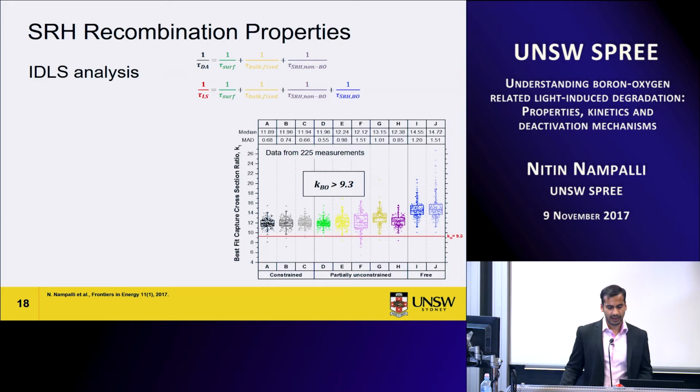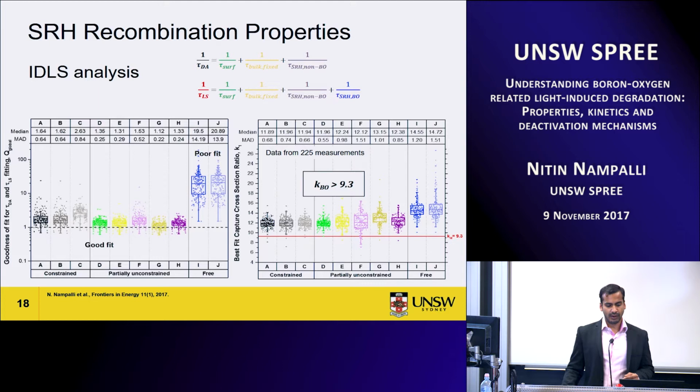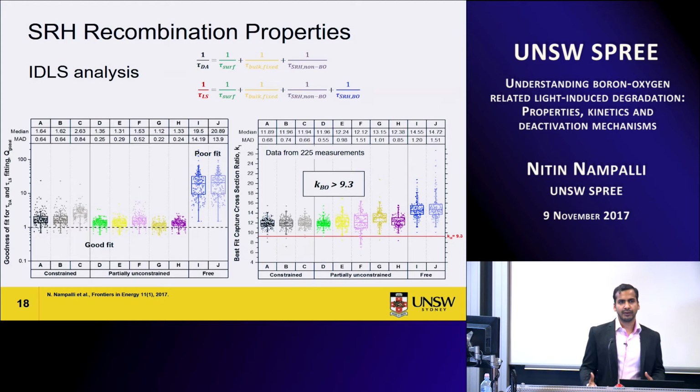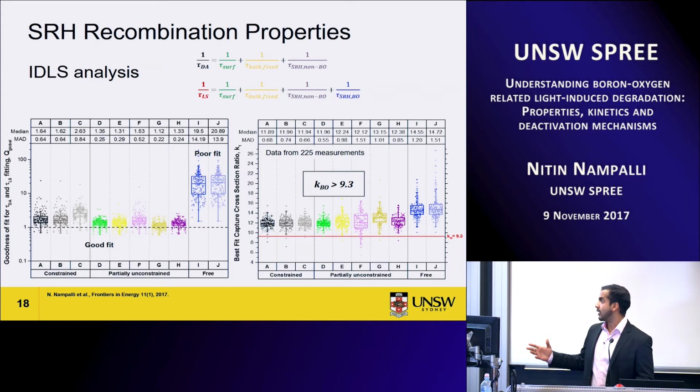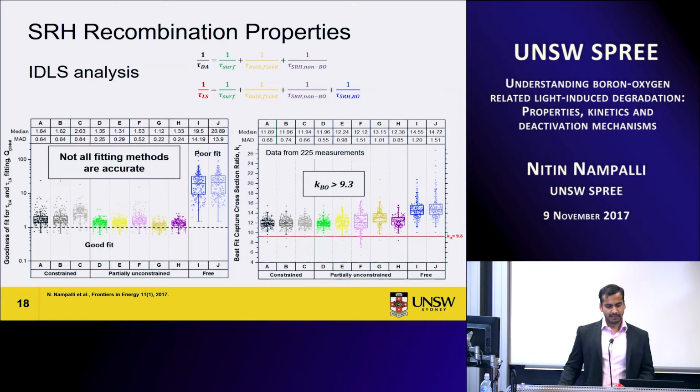Now, for each method, there's also a big range of variation in the K values. That's because not all fitting methods necessarily result in a good fit to the data. So that's something to consider as well. In this case, you can see the methods I and J on the right side have a very poor fit, whereas the other methods seem to have a better fit to the lifetime curves. So that's a conclusion: not all fitting methods are accurate, and you should really consider this when you're trying to